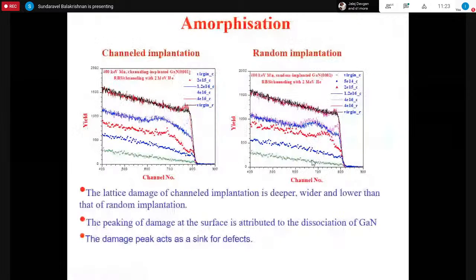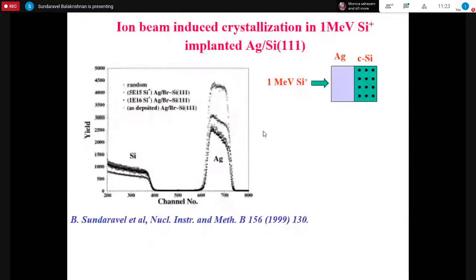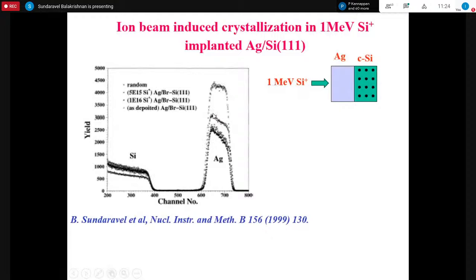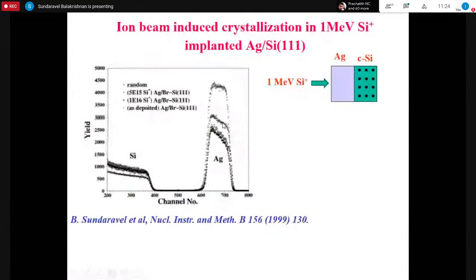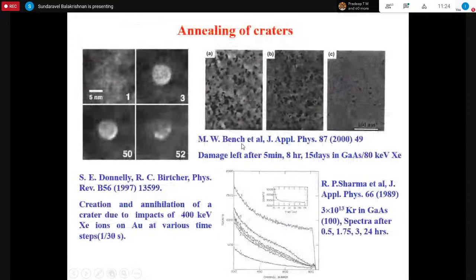And as such, when we do implantation along this channeling direction, your damage will be much less compared to implantation along random orientation. And upon irradiation, for example, here is the RBS spectra from a silver thin film on silicon, and this is the channeling spectra for the as-deposited sample. And upon annealing or upon irradiation with 1 MeV silicon ions, you see that this damage is getting reduced as the layer is becoming more crystalline, which is seen from the reduced yield. For gallium arsenide, if you do the irradiation, that self-annealing will be faster.